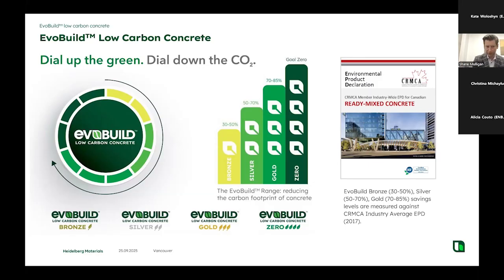provide a carbon reduction in the range of 30 to 50% versus those benchmarks, we call that an EvoBuild bronze product. If it's 50 to 70% savings, that's EvoBuild silver. 70 to 85, it's gold. And then if one day we can reach the goal of a net zero product, we would call that an EvoBuild zero product. That's not to say that every one of these levels are available in any given market.